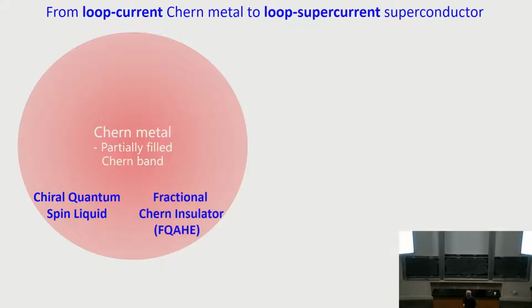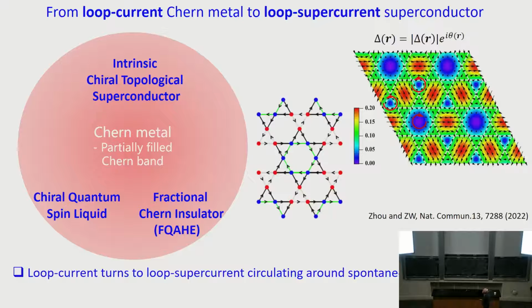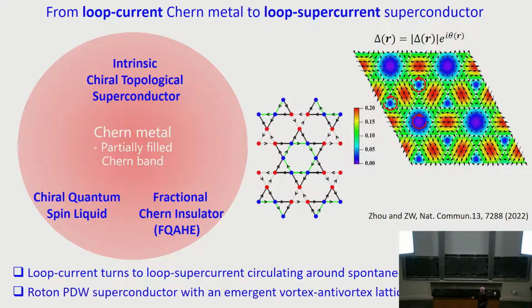We could have fractional Chern insulators or a fractional quantum anomalous Hall state, which has just been observed since a couple of months ago in these twisted TMDs, right? And there is a third possibility that it just goes to a superconducting state, and then I would argue it goes into an intrinsic chiral topological superconductor because of topology, because of the Berry curvature that's carried by this band. Another way of thinking about this is you have this loop current going around, and once you go into a superconductor, these loop currents cannot just disappear, so they would have to circulate around vortices and anti-vortices, forming a vortex-antivortex lattice, right? And that lattice is what the PDW is all about, this emergent vortex-antivortex lattice.